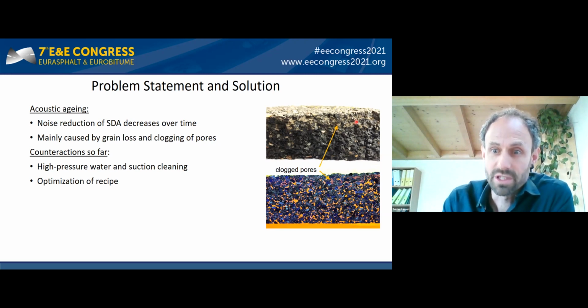It is important to notice that there's a different clogging mechanism for SDA than, for example, for regular porous asphalt, where the clogging normally occurs bottom up. It was tried with water cleaning and high pressure and suction to avoid this clogging, however, without success.